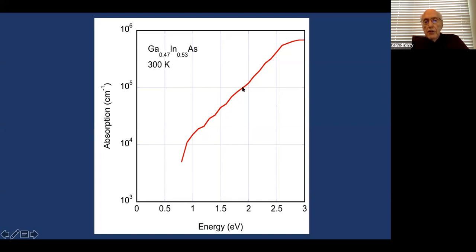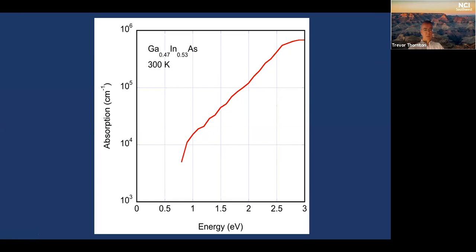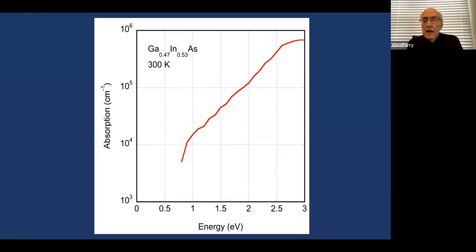But if you get to 10 to the 5th, that means the average electron is being absorbed in the first 1/10 of a micron from the surface. So at 3/10 of a micron, 300 nanometers thick, 95% of all the photons coming in have been absorbed in the gallium indium arsenide. And so that's good. You want to try to do that and keep all these electrons and photons in the material where they're going to be useful and in the depletion region. So you want the depletion region to extend over those 3/10 of a micron. And you do that by doping. Okay, so that'll make a good cell.